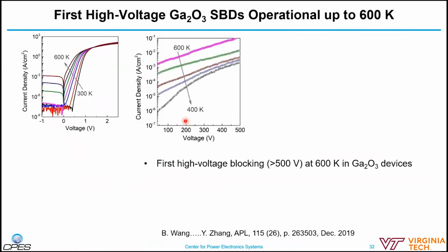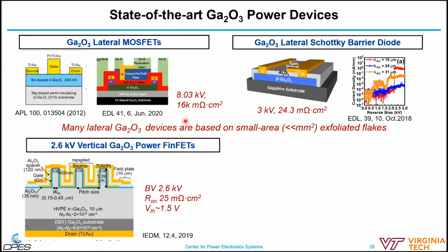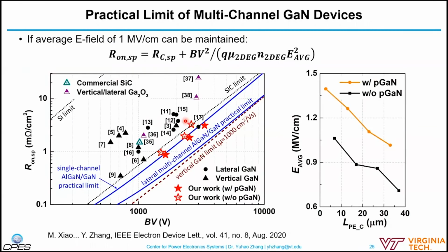Let's go back to here. Theoretically speaking, if we stack more 2DEG channels, we can definitely make the sheet resistance smaller, and so the total 2DEG density will be increased. But it should be noticed that if we don't do the delta doping at each of these 2DEG channels, the total 2DEG density won't increase proportionally to the number of the 2DEG channels.